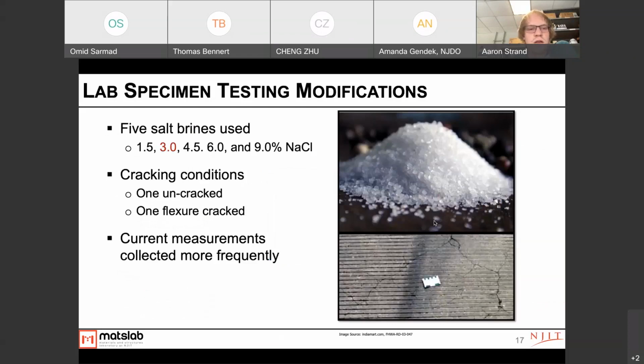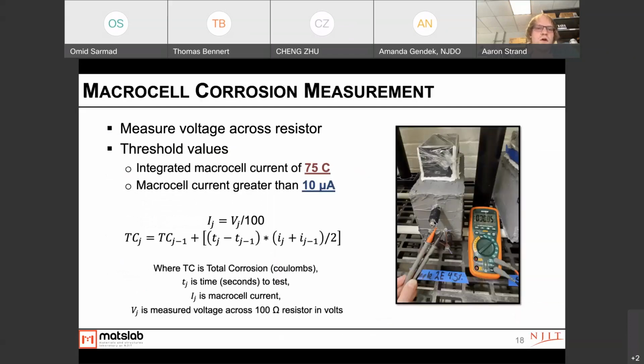So we used 5 different salt brines: 1.5, 3, 4.5, 6, and 9% sodium chloride solution. The 3% is what is specified in ASTM G109. We had one uncracked specimen and one flexure cracked specimen. And again, the current measurements were collected more frequently than specified in ASTM G109. How we did the data measurement was we measured the voltage across the resistor, and this allowed us to calculate the current within the cell. Basically, the threshold value in ASTM G109 for an integrated macrocell current is 75 coulombs. And if there's a macrocell current greater than 10 microamps, that indicates that corrosion was able to initiate and possibly was occurring, but it didn't definitively prove that it was happening.